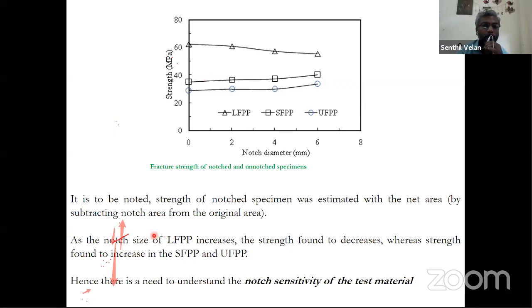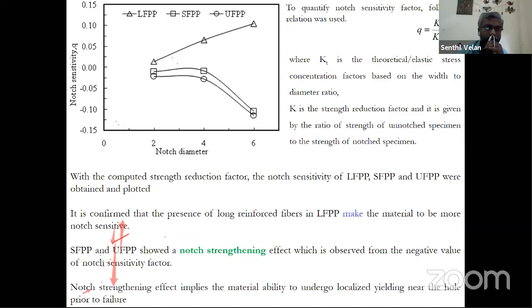Not only that, the fatigue aspect. We are all familiar with notch sensitivity and how to get it, KS and KT. So you can clearly see that these two, the unreinforced and the short fiber, the notch sensitivity is dropping down, whereas this one is increasing. So in this case we call it a strengthening effect. Why is the strengthening happening? Because this material has the ability to undergo localized yielding. Localized yielding will happen near the hole, whereas that possibility is not there in the case of brittle or high strength class of material.